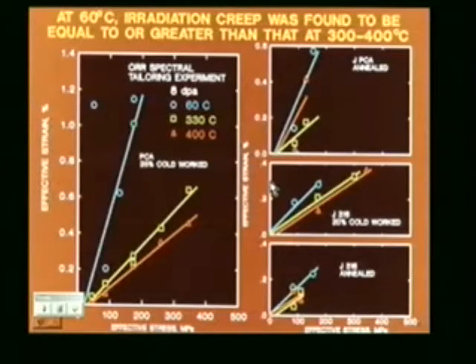And the point is, if it can move around obstacles, get around obstacles, then we can have glide again. So the irradiation hardening that we said resulted from putting a lot of defects in and tying up these dislocations, we only said half of that earlier, but that's what happens. Now we can get them to move around.